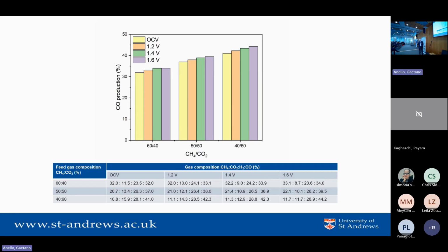It doesn't start off at equilibrium. So the initial gas composition is somewhere between what we feed in and what would be full equilibrium, because we're using an electrode, not a very finely divided catalyst.